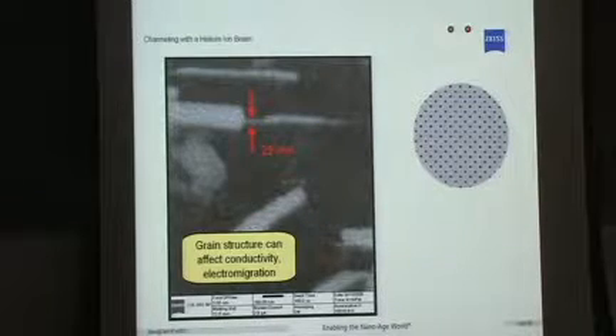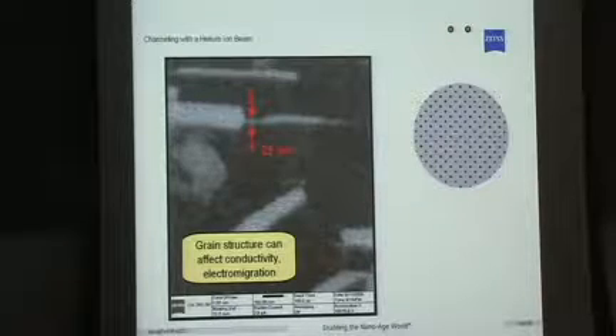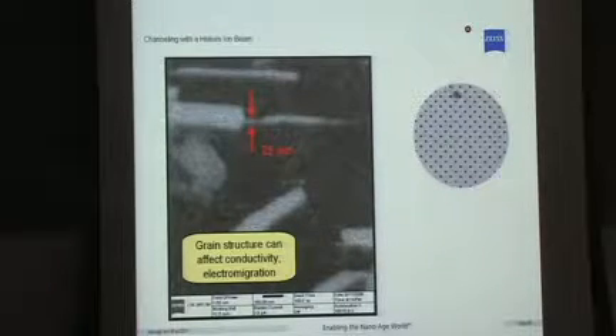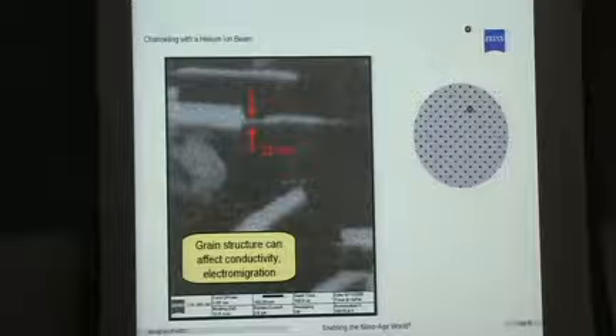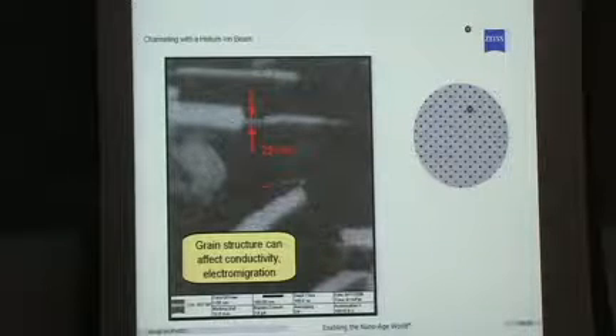But if you look over here in this little animation, I'm going to launch a helium ion into this material that is not oriented parallel to the beam, and it bounces all around. It essentially gets lost, dissipates all of its energy fairly close to the surface, follows a lot of bounces. That would be a bright area in this crystal.